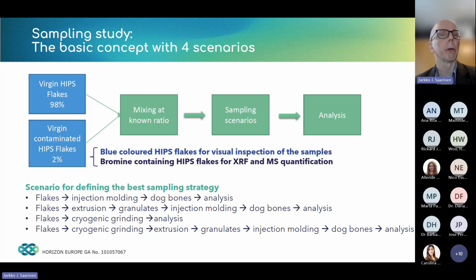this is the basic concept that we have been developing within the project. So there are 4 scenarios. What we have as starting materials is virgin high-impact polystyrene flakes. We selected 98% of these virgin flakes, and then 2% of the material is contaminated either by using a blue-colored colorant for the means of visual inspection of the samples, and then, in order to do more quantified analysis, we also added 2% flakes with a known concentration of the brominated flame retardant, which we can then quantify using either X-ray fluorescence spectroscopy or mass spectrometry characterization and quantification. For the 4 scenarios, we mixed these with known ratios. And then the sampling scenarios were that first we just take the flakes, do injection molding, make dog bones, and then do analysis.